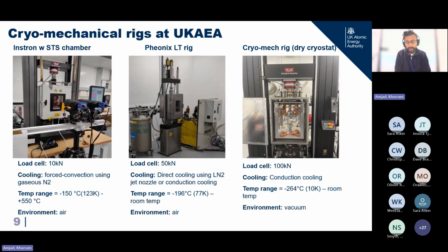So in our lab, we have got 3 different rigs that can do mechanical testing at low temperatures. The first one is an Instron rig with the STS chamber. That has a temperature range of minus 150 degrees centigrade to plus 550 degrees centigrade. And we have done extensive work on it to deploy stereo digital image correlation. I'll be presenting some results from this rig in the later slides.